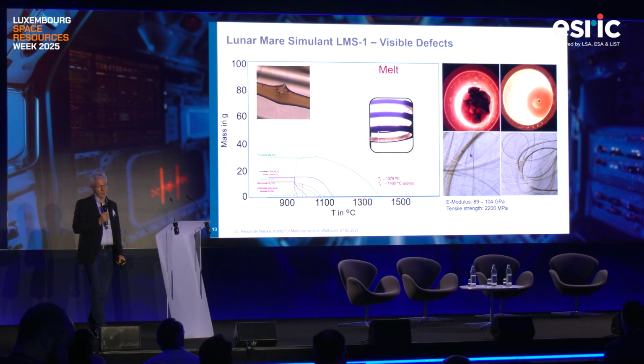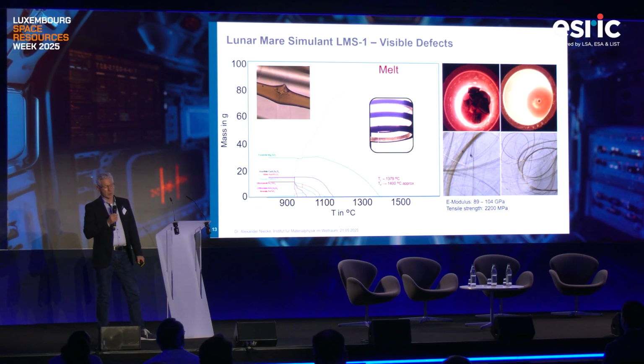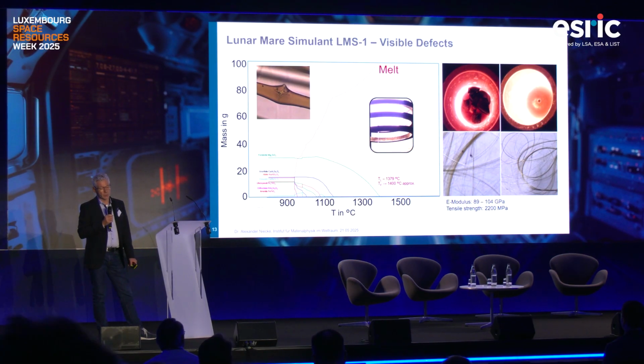LMS1 was also possible to be produced. You can see these imperfections in more detail, macroscopically, and on the microscopic scale using light microscopy, imperfections and inclusions are visible, and these inclusions have a detrimental effect on the spinability.